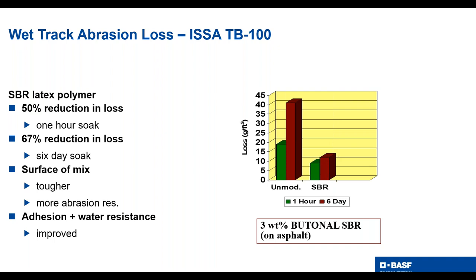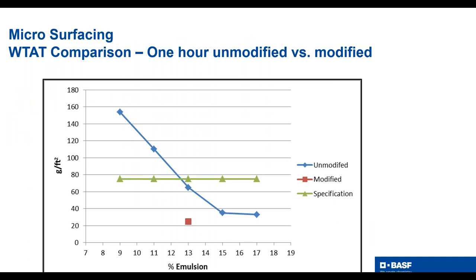But I think I mentioned the balanced mix design and how this was the original balanced mix design approach. But when I was doing a lot of microsurfacing designs, folks would ask me, well, why are your designed emulsion contents higher than some of your competitors'? And the original idea for this 1 hour wet track was to give you the asphalt content of an unmodified system. As you saw on the previous slide, the polymer modified system did very well. So what I had done is the green line on here, close to green if you see it on the screen, is the specification, which is 75 grams per square foot.